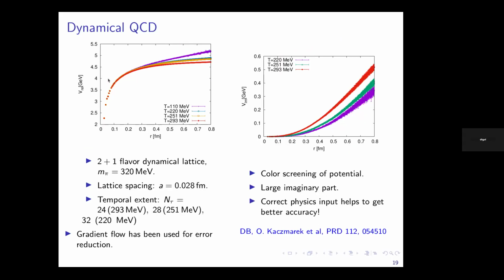Okay, so I have a question here. Sure. In the case of dynamical fermions, you have this confinement-like behavior at 110 MeV, right? Right. But that is up to some distance, right? Because there will be string breaking. Yeah, there will be some, after some distance it will saturate, but that will happen roughly after 1 Fermi or 2 Fermi, after the Lambda QCD scale. But here we have plotted up to 0.8 Fermi. So if you would have plotted more, then we should show a saturation here.